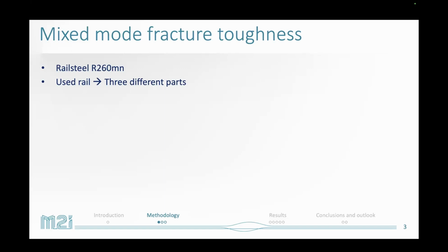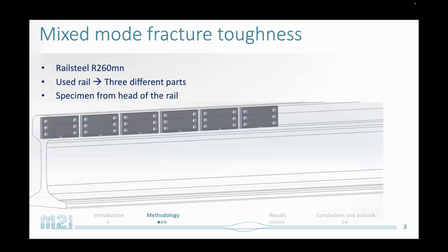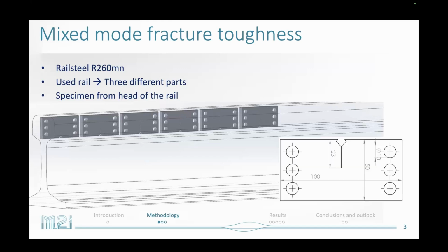And we have used rail. So the specimens I have are made of the remainders of the rail you saw in the previous slide. And we make so-called compact shear tension specimens out of the head of the rail, because that's the place where these squats, these fatigue cracks in practice occur. So here a schematization of this specimen, but I will come back to that in a second.